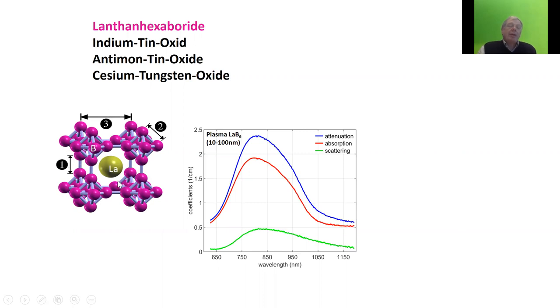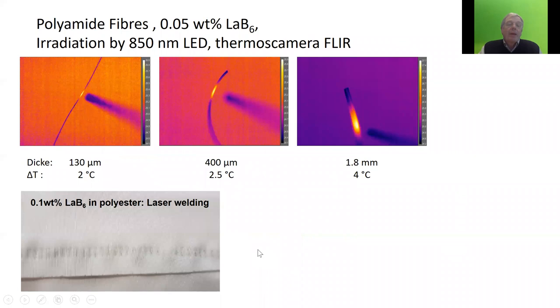And as an example here, the lanthanum hexaboride, which also has a plasmonic resonance band in the range of the near infrared in here. Now, for example, here we have a fiber of nylon, which was blended with the small lanthanum hexaboride particles. And then you shine infrared light on it. You see local heating at this spot. And the local heating even can cause bending and change the shape of the material in there. You can use this for welding.